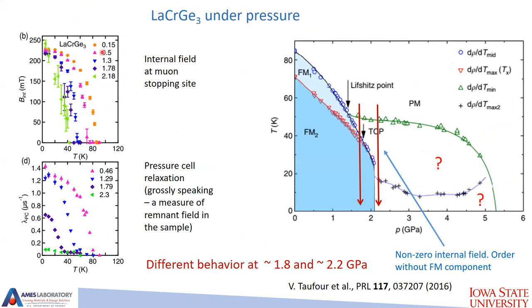So for low pressures, let's say for half a GPa, the signal from the sample and the signal from the cell are in a sense similar. They start at the same or very similar point. So ferromagnetism, fine. We kind of knew this. Let's look at 1.8 GPa. So it's this line. And right here, we already see some difference. One of the differences is that we start to see signal in the sample at temperatures higher and measurably higher than the signal from the pressure cell.